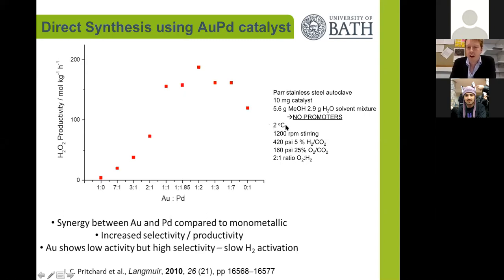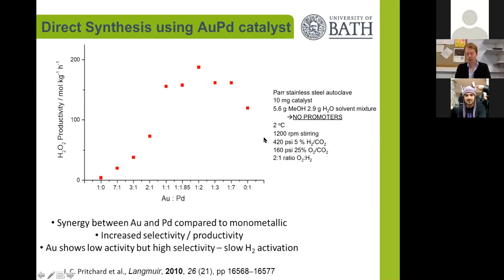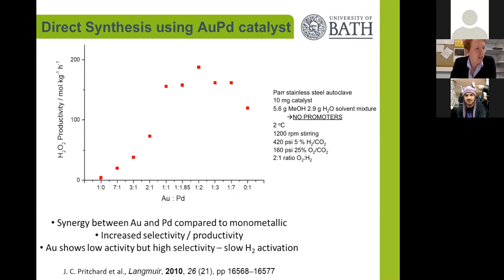We conduct the reactions at very low temperatures, just below ambient at two degrees Celsius, with high stirring and high pressures of gases around 40 bar in total, with a hydrogen-to-oxygen ratio of one-to-two, and CO₂ as a diluent to push us outside of the explosive regions.